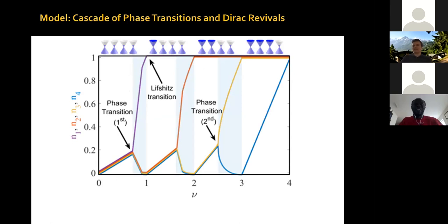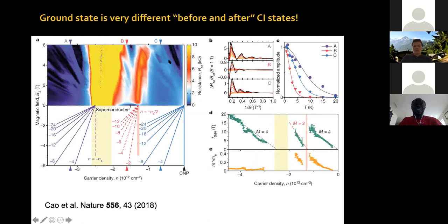So this puts some, shines some light on one of the puzzles that we already saw in our original 2018 paper, which I mentioned yesterday. So if you look at the Landau fan diagrams, at the Shubnikov-de Haas oscillations, at the frequency of the Shubnikov-de Haas, at the effective mass, at the Landau fan diagrams and the degeneracies, okay. Here I'm plotting from charge neutrality towards holes, okay. As I mentioned yesterday, we saw that the degeneracy of the Landau fan diagram seemed to be 4 stemming from charge neutrality, and then also from the remote band, but after filling factor -2, after the correlated insulator state for holes, it seems that the degeneracy of the Landau fan diagram was 2, okay, which was a little bit puzzling. Also, there seemed to be a reconstruction of your Fermi surface at filling factor -2, for holes.